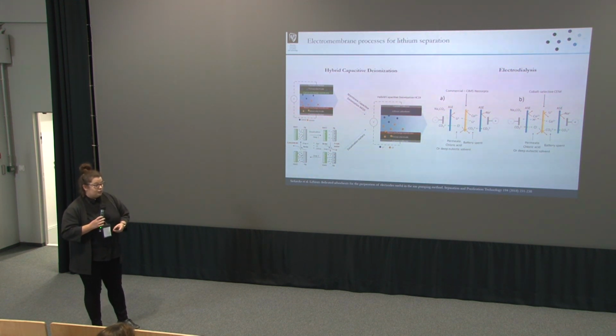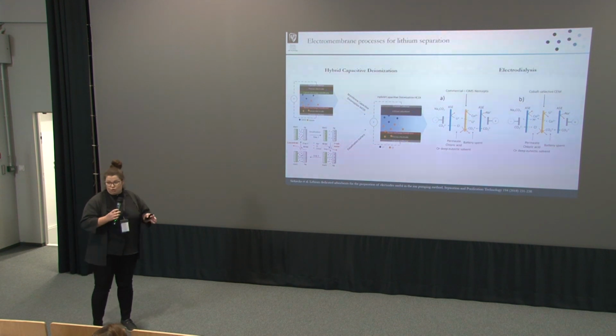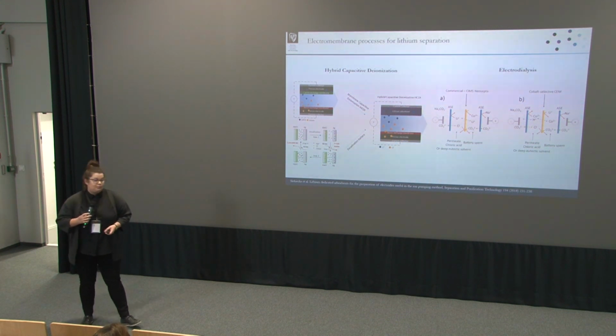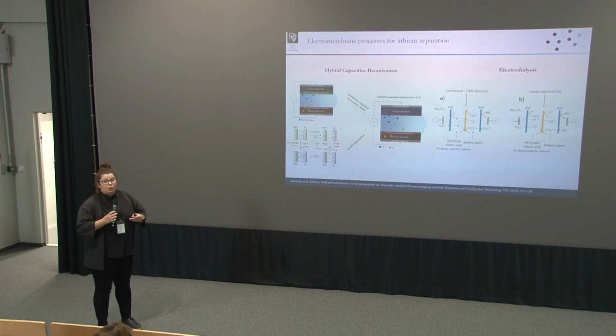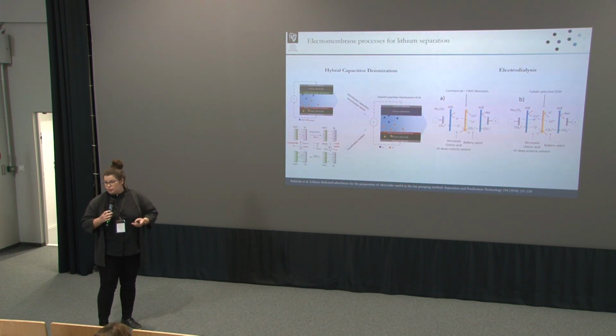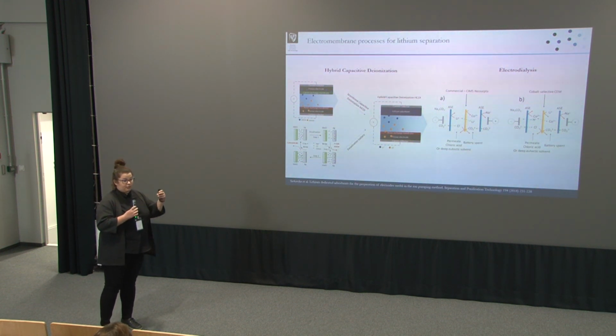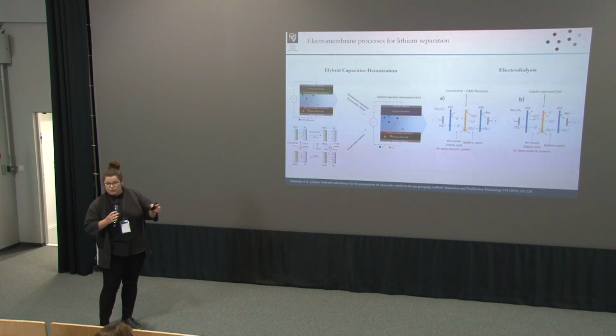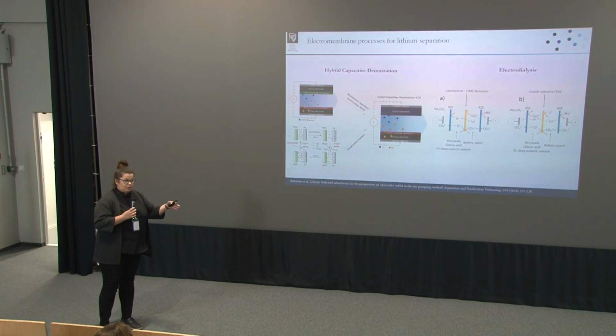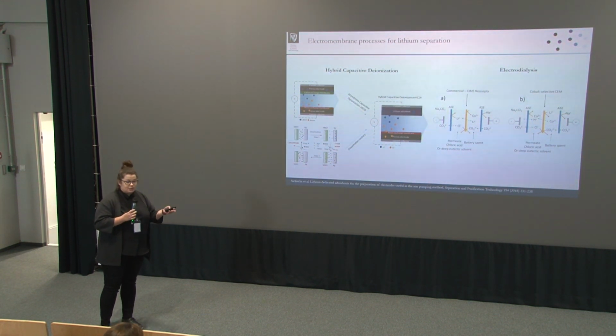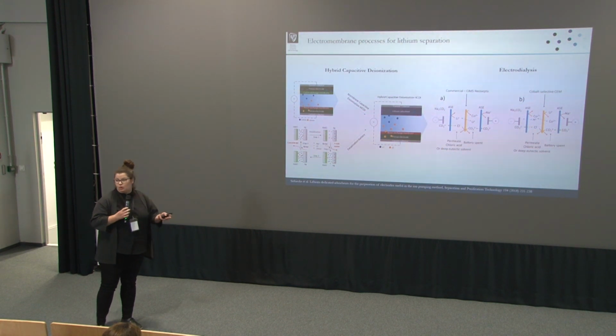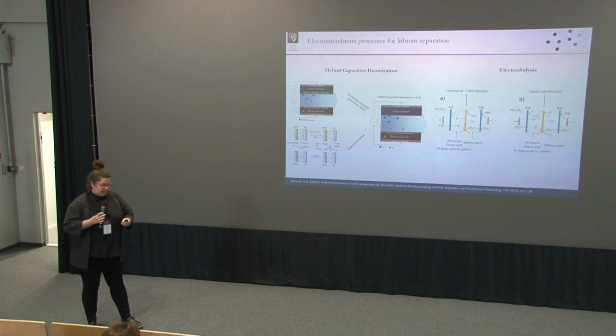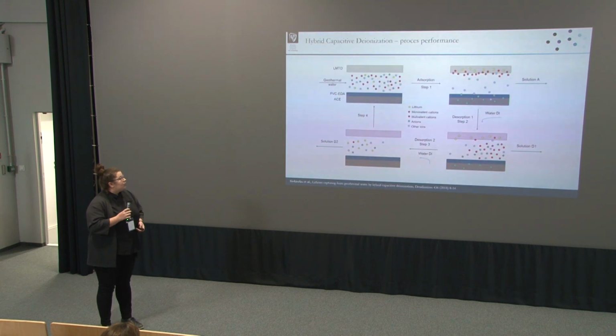For releasing lithium from the lithium, cobalt, and nickel mixture, I apply electrodialysis, where we can find two different strategies: either focus on directly releasing the lithium from the mixture, or focus on the transition metal ions, cobalt or nickel, and separate them from the lithium.